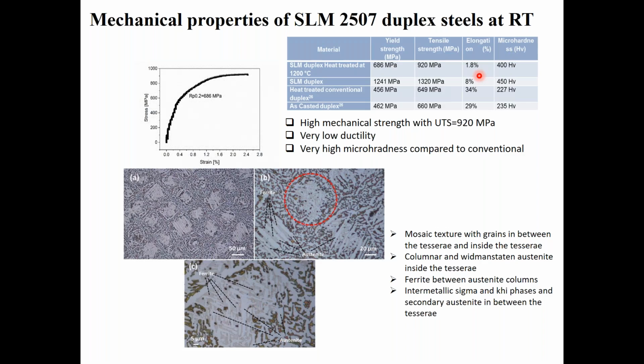We found that although there is a phase transformation from ferrite to austenite, giving the duplex structure, at the same time we precipitate intermetallic phases like sigma and chi phases. That is responsible for the low elongation in these states. So for room temperature application, with such a heat-treated structure, we don't get promising properties. But we will see that these precipitates actually contribute towards high temperature mechanical stability in the steels, which I will show later.